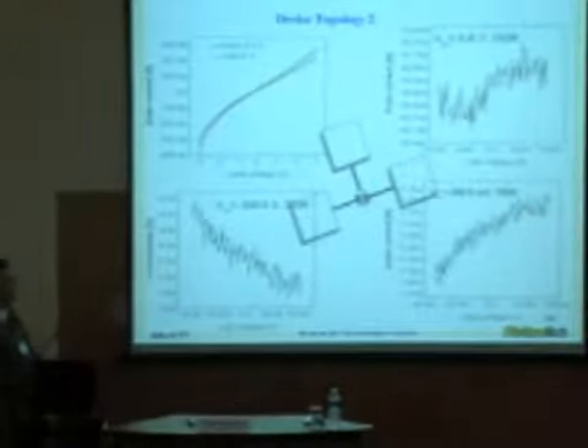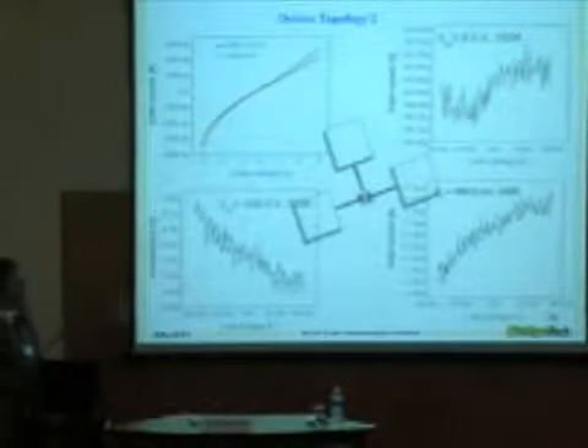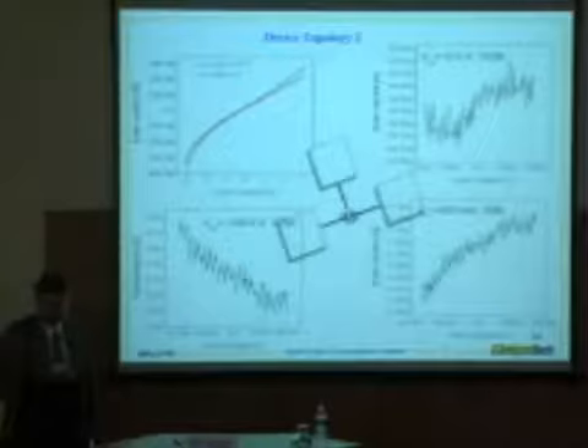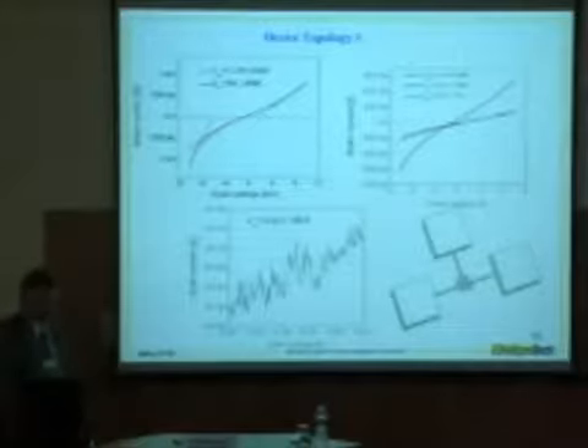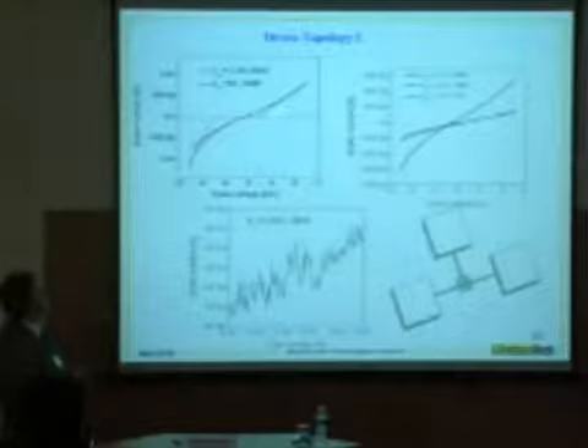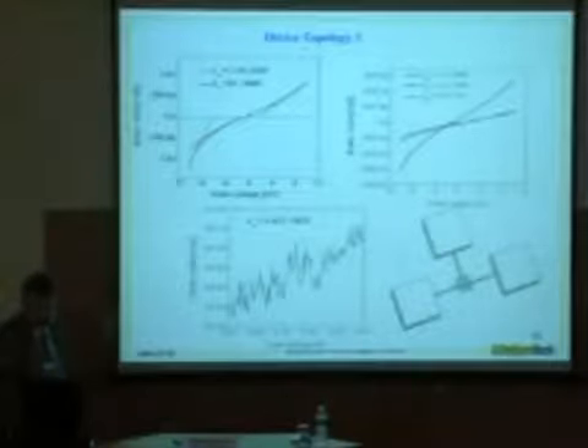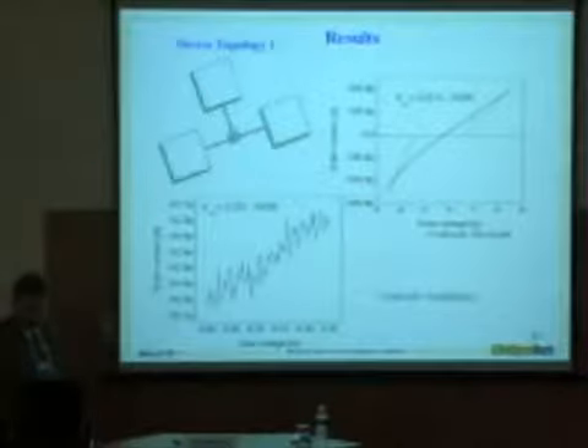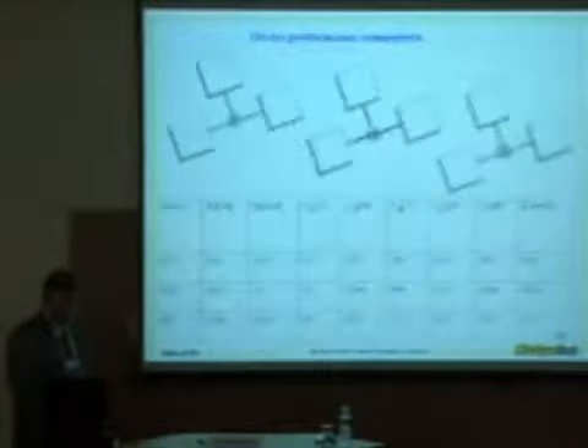Another graph over a slightly different range, I believe also at room temperature. Anyway, for the various topologies we've looked at these results, and we do have confirmation in these outputs that we are indeed seeing these Coulomb blockade events and quantum confinement results in the outputs. Again, various device topologies give slightly different behaviors. In this case, we see much stronger curvature at the extremes of the conductance curve, which is potentially a good thing. And we see this for a variety of different devices, spacings, and configurations. So we have confirmation that, yes, we do see room temperature SET behavior.